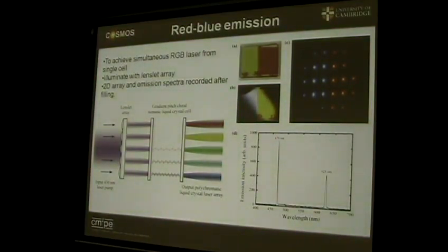If I use a combination of the coumarin and the pyrromethene dyes, I can get the right absorption and the right emission. And then just for a single cell here, that would be on 2 elements. A green reflector and a red reflector, giving you, in this case, a blue output and a red output. Okay, and that's the spectral purity. Those are arrays recombined in the far field, and they're very narrow line widths. And let's stress that they're very narrow line widths, red and blue. But we want to go on from there.